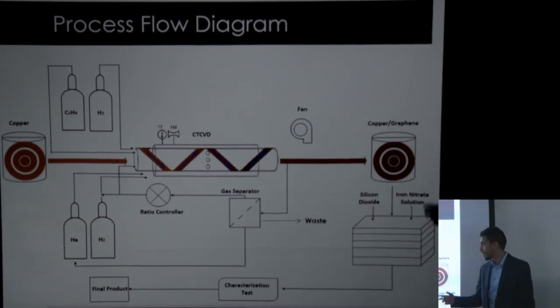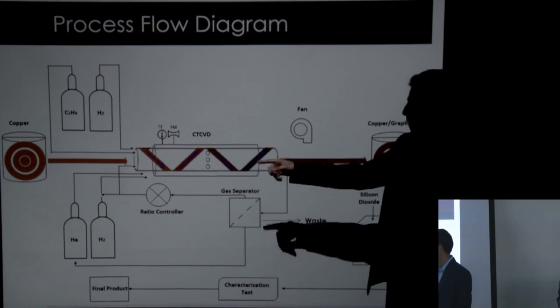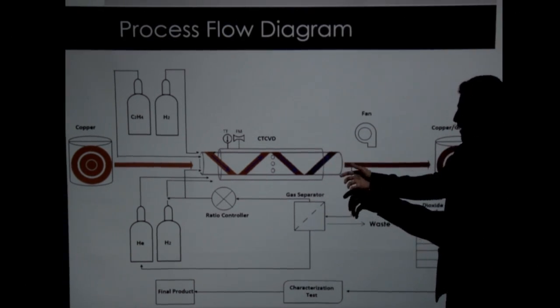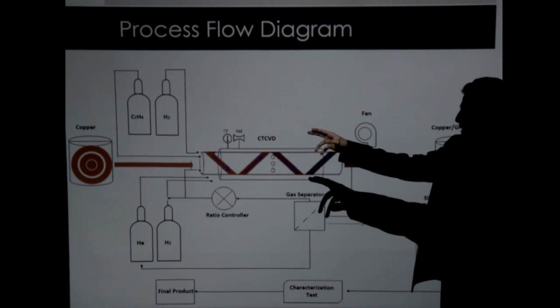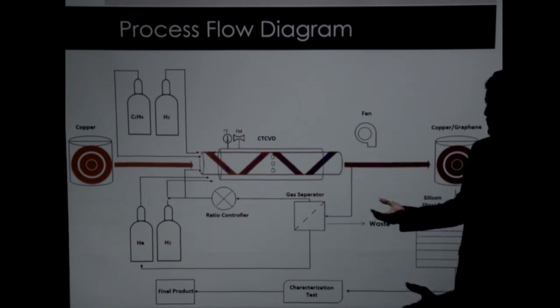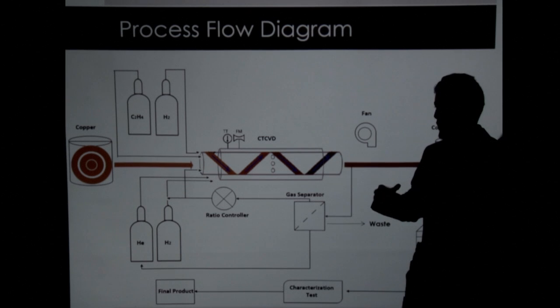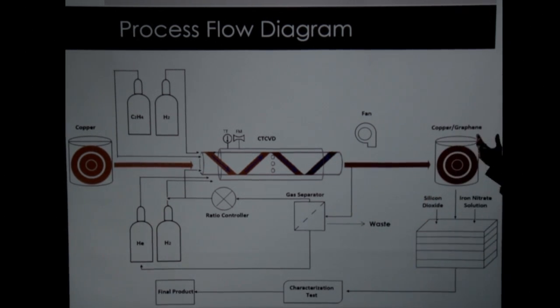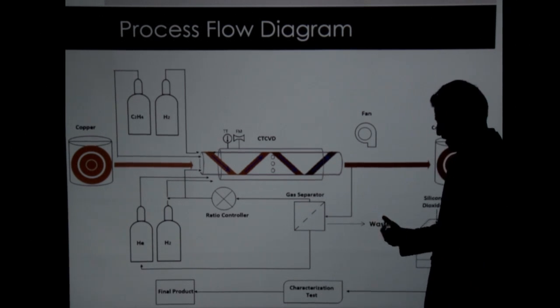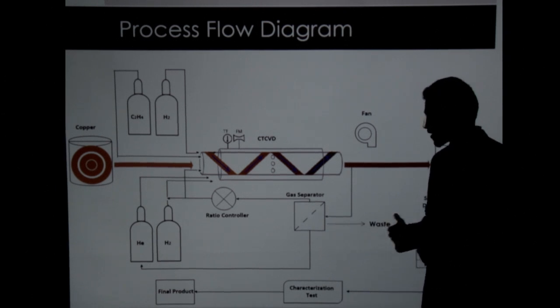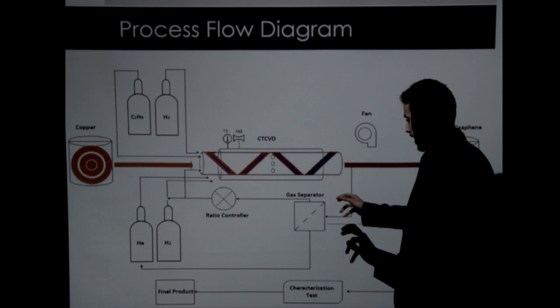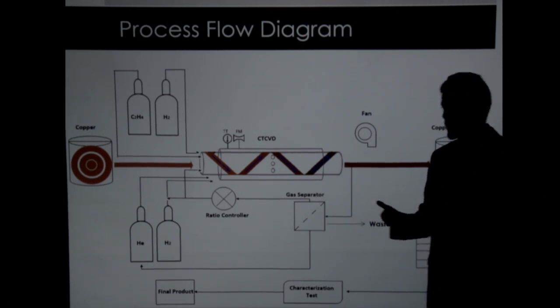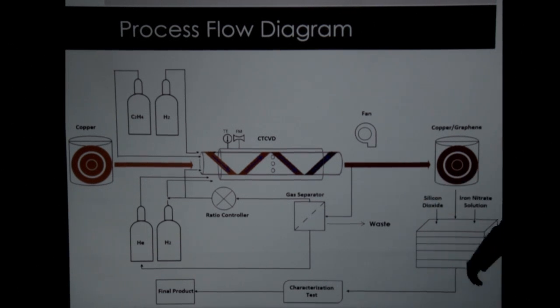Here's a process flow diagram of our system. So the copper foil is wrapped around the inner tube of the CVD reactor, and ethylene and hydrogen gases enter the system, and in the presence of high temperature, the graphene layer forms on the copper. Then the copper graphene layer goes to a transfer step where the graphene transfers from the copper foil to a silicon dioxide. After that, the product goes through a couple of characterization tests, and if it passes, then we get our final product. Also, one thing to mention is we added a recycle stream to our process, to recycle the unused gas in our process, which Faris is going to talk about in more detail.